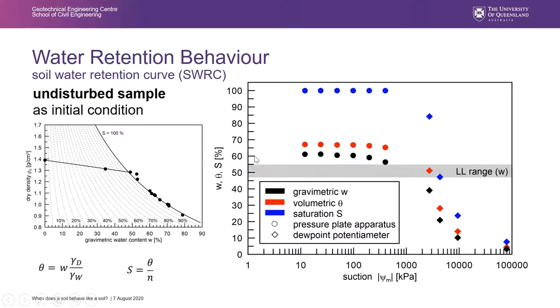Again, the liquid limit range, as you can see, is here in between, at a water content which is smaller than the natural water content. This 60% is around the natural water content. And we only reach that water content in this test at suctions which are very, very high. Accordingly, we have here the so-called air entry value. As you can see, we have fully saturated conditions up to this point, where for the first time air enters the soil and we get truly unsaturated conditions. And this happens at 400 kilopascal, which corresponds to a height of 40 meter water column.